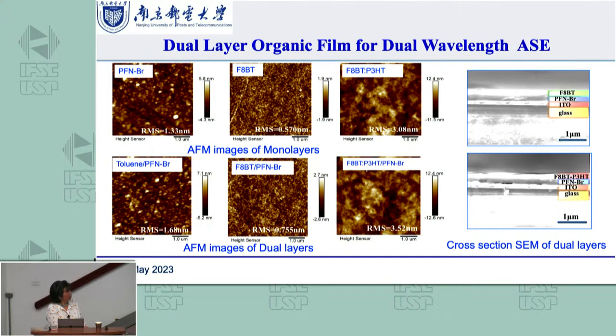So we did the SEM measurement. We can see clearly the ITO, then the first layer and the second layer. We can see the interface very clearly, so the film quality should be reasonably good. Also the AFM shows the quality is not bad.